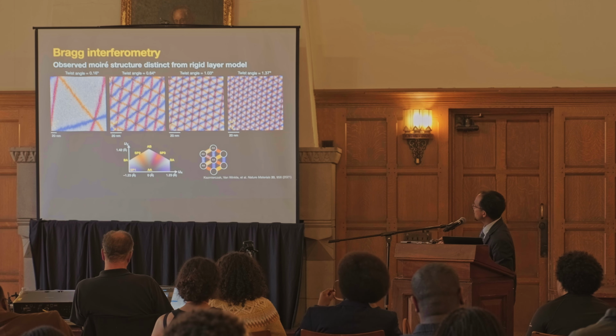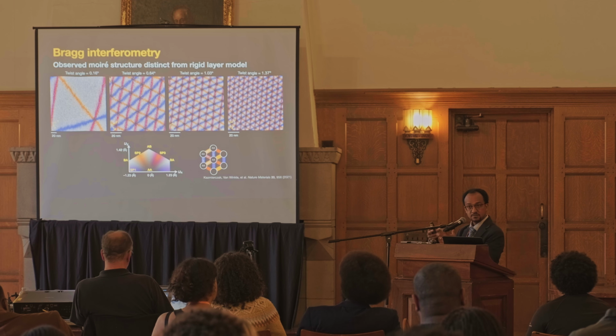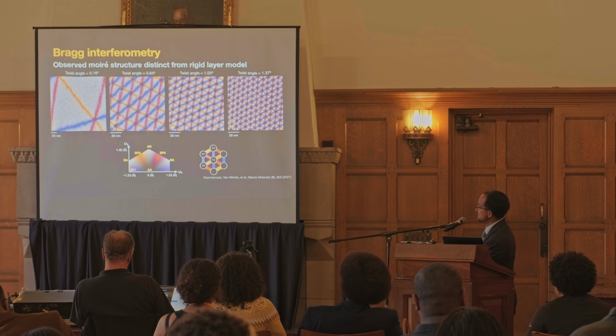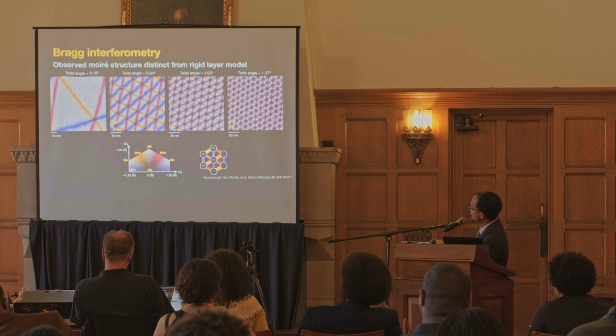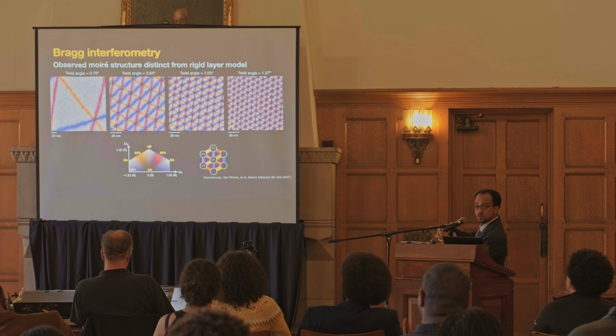And when we do that, we find, whoa, this observed structure is very, very different from this cartoon that everybody was using with these rigid things. Something has gone on that has actually caused some of those regions where the atoms are right on top of each other to shrink in size and the other regions to expand.